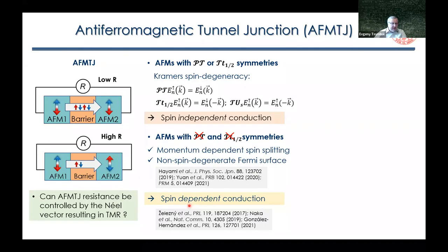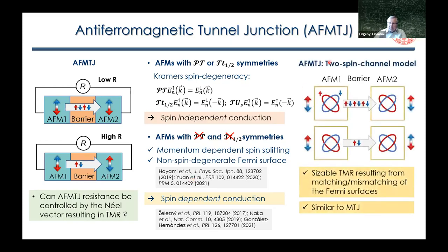So even though we have net magnetization equal to zero, due to the fact that we have momentum-dependent spin splitting, the conduction may be spin-dependent. And please look at these publications which discuss this idea in a more generic way. So from that perspective, we can use this kind of antiferromagnets in an antiferromagnetic tunnel junction. And if you use the same two-spin channel model as I used for ferromagnets, we can argue that this kind of antiferromagnetic tunnel junction may have a non-zero tunneling magnetoresistance effect.